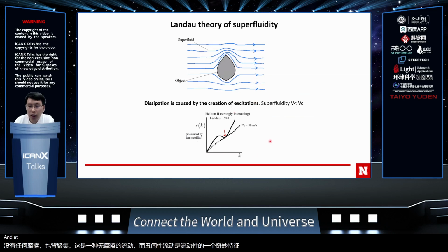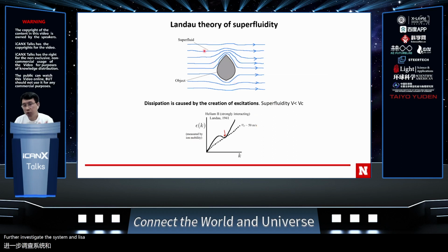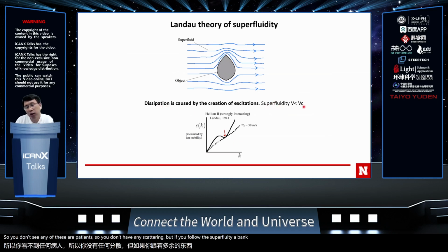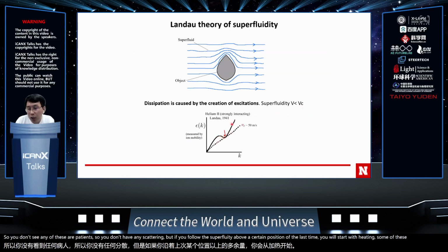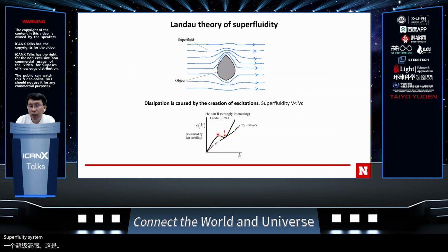Later on, Landau further investigated the system, and he said that if you flow the superfluid at a lower speed, indeed you don't see any elementary excitation, so you don't see any dissipation or scattering. But if you flow the superfluid above a certain critical velocity, you will start to hit the elementary excitation spectrum in the superfluid system, and then the superfluid no longer maintains superfluidity and breaks. There's a transition predicted by Landau.